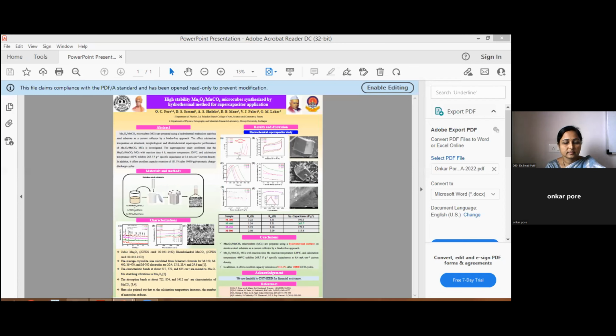Then the results and discussion. The as-prepared samples were characterized by electrochemical supercapacitor study. Figure A shows the electrochemical impedance spectroscopy study of the as-prepared samples. Here we can see the Nyquist plot of the as-prepared sample. The estimated parameters, that is solution resistance and charge transfer resistance from this graph, are mentioned in this table.